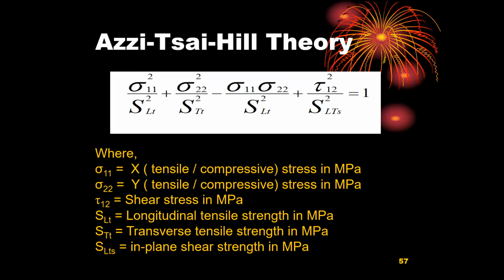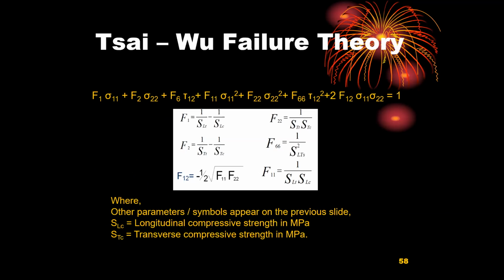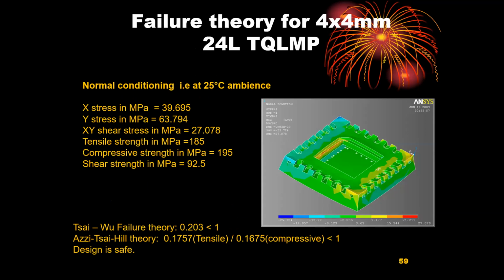Coming to the generated stresses in simulation and then the actual test done, we were happy. We applied the Azzi-Tsai-Hill theory and then the Tsai-Wu failure theory, because the compressive, tensile and shear strengths of the materials were different, or the encapsulants were different, and we had to go in for some of the directional properties also, as it was very thin and behaving like a layer. When you apply the failure theory, the X stress or the Y stress or the XY shear stress could be considered, and then the tensile, compressive, and the shear strength could be considered.